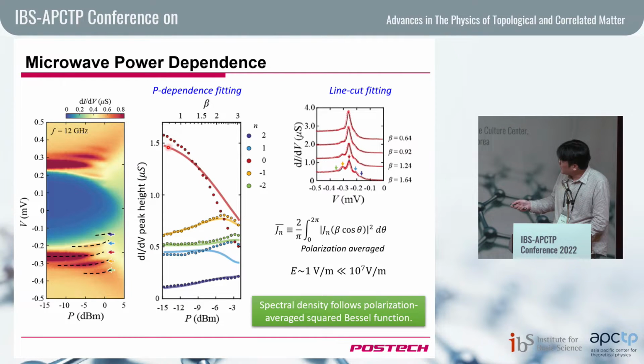And these are data, and the solid lines are theoretical calculation, which fits okay. And the line cut looks even better. But anyway, when we are fitting this, our electric field was on the order of 1 volt per meter. As compared to the 30 terahertz mid-IR pulse light case, where the electric field was 10 to the 7th volts per meter. So as expected, the needed electric field was indeed reduced by a factor of 10 to the 7th.